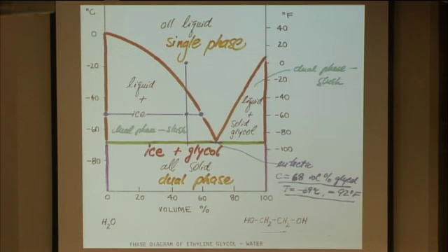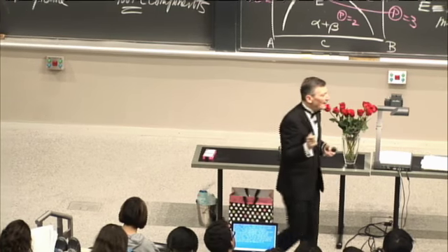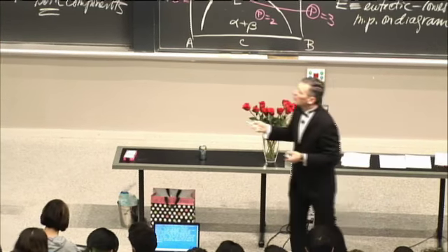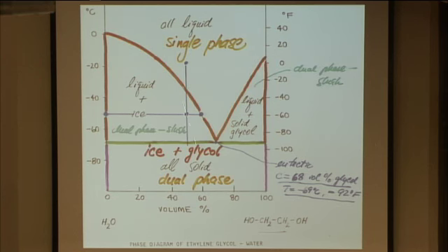This is in volume percent, because that's the practical unit. When you mix glycol with water, you do so by volume, not by mass, or certainly not by moles. So if you mix 2 parts glycol with 1 part water, you'll end up with a eutectic of -69 degrees C or -92 Fahrenheit. So that ought to take care of your driving needs. All right? Now, practically speaking, we put in an equal volume mix. So it's about a 50-50 glycol-water mix. And that gives you liquidus depression down to about, not quite -40, it's about -35 Fahrenheit, which ought to take care of most people's driving needs.